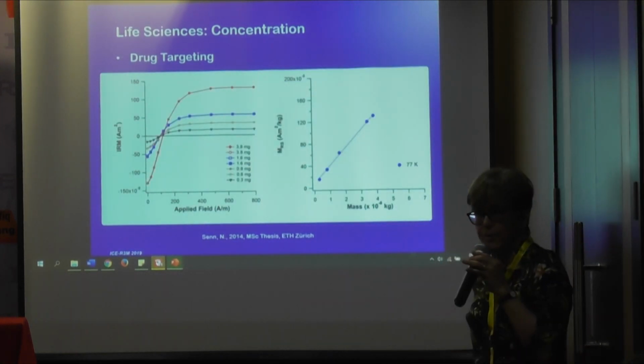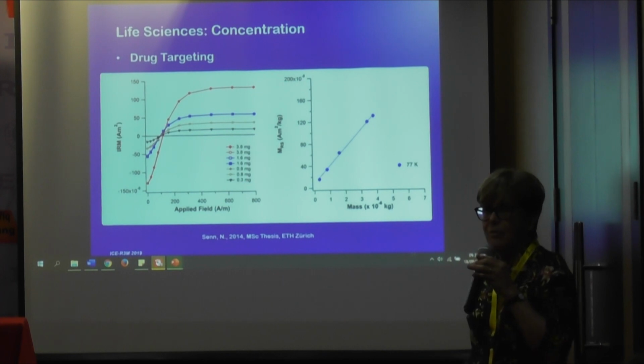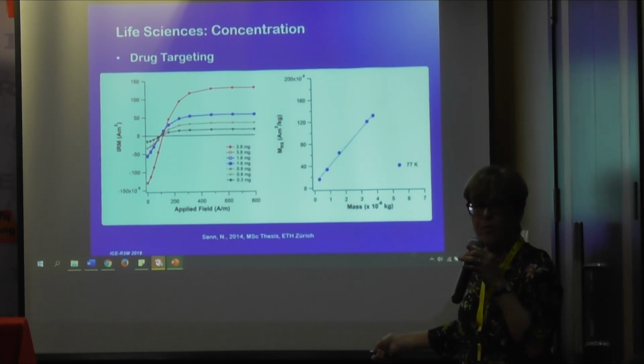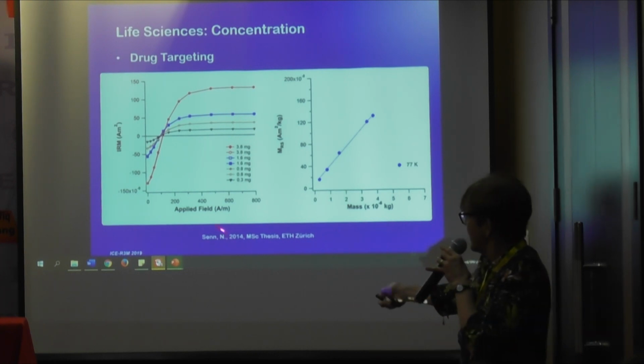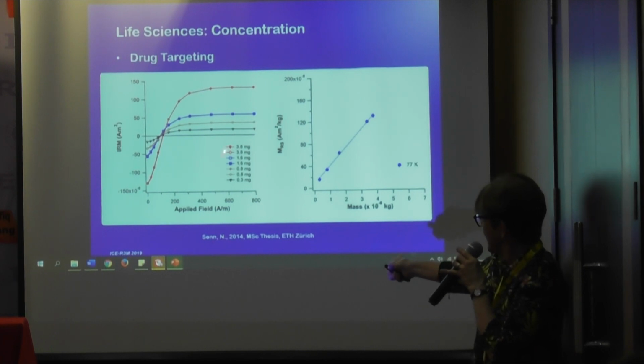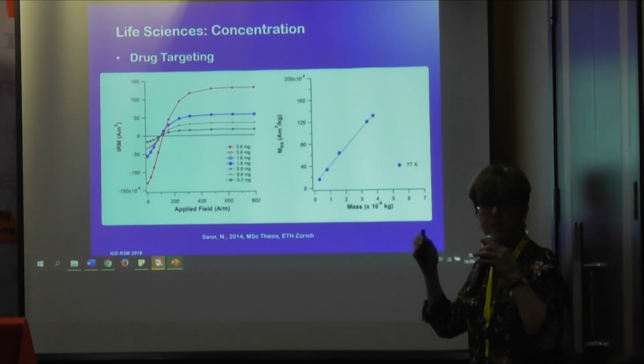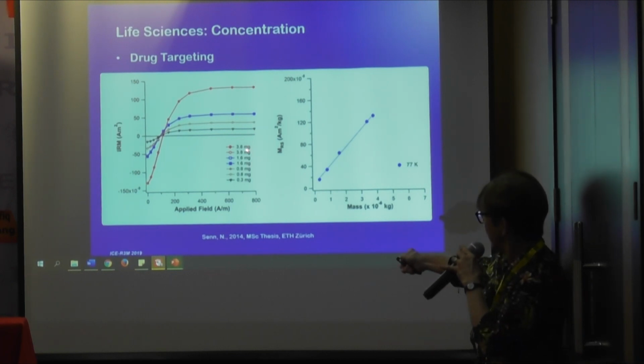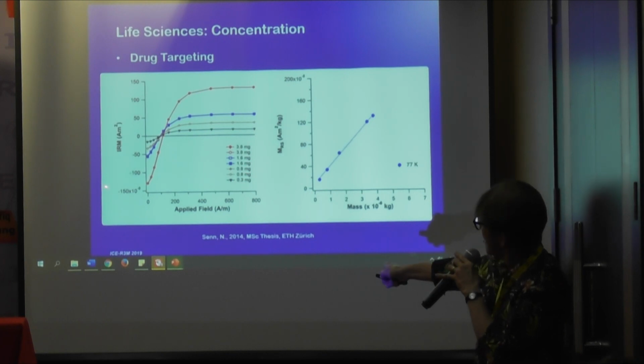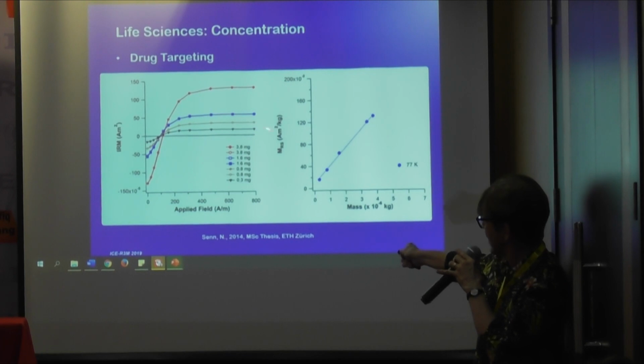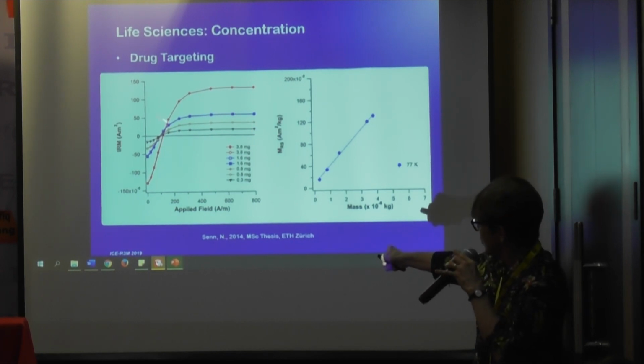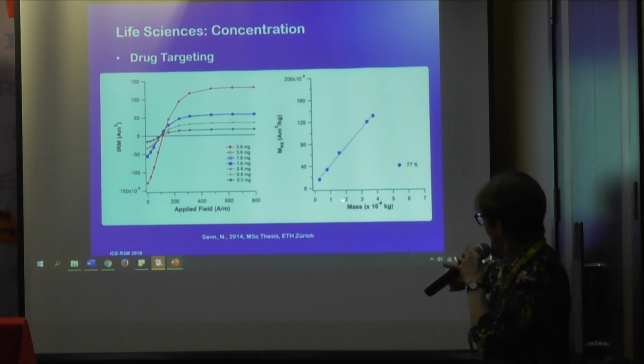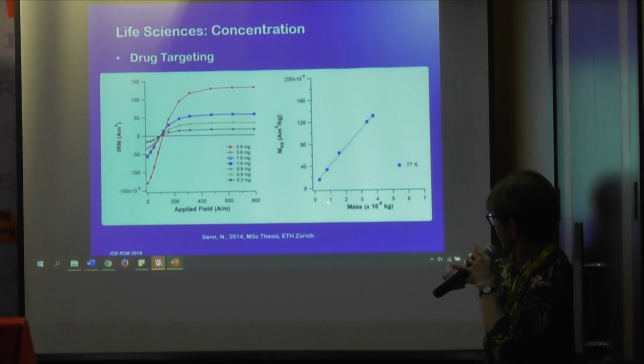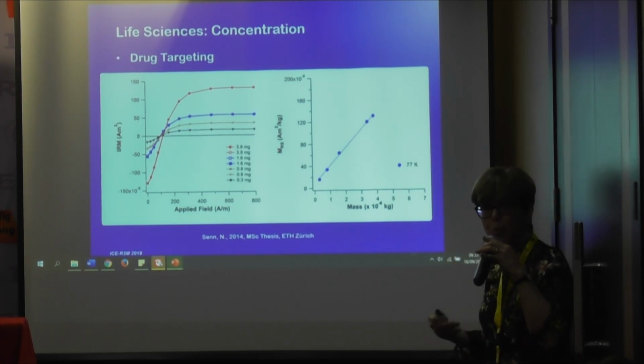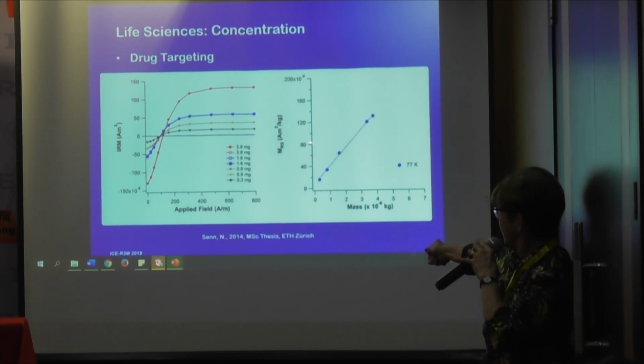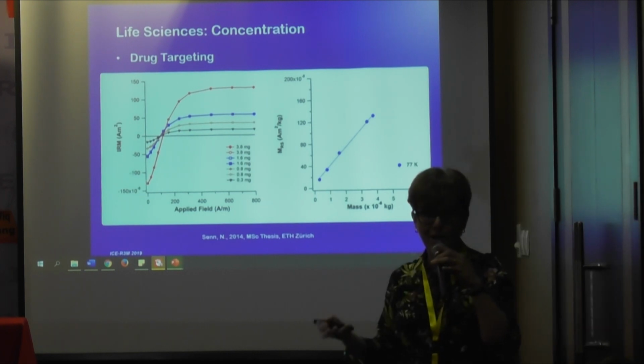Okay, next. So the first thing we did is we wanted to make sure, how does it scale? We want to know how much of the drug or the nanoparticles are reaching the tumor. We wanted to know, can we actually look at this? So my student prepared, as part of a master's thesis, different concentrations of just this nanomaterial itself. We had 3.8 milligrams, 1.6, 0.8, and 0.3. We measured the IRM acquisition curve. We got the saturation remnant magnetization. We also were able to check the remnant coercivity of the material. And then we could see this remnant saturation as a function of mass. That gave us a calibration curve. So later, when we measured the tumor tissue, if we measured this remnant saturation, we could tell how many particles were actually in the tumor.